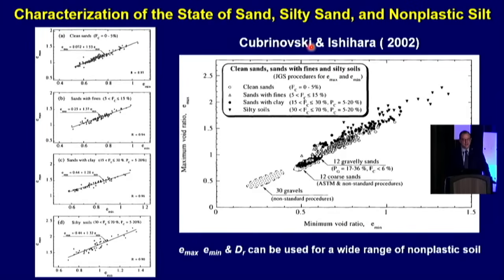They realized in 2002 in the Soils and Foundations journal that they could characterize the state of sand and a silty sand using e_max and e_min, the maximum void ratio and the minimum void ratio. They could use the concept of relative density even for soils that had more than 5% fines, which the Japanese standard is supposed to be restricted to. In the US, we're up to 15%.